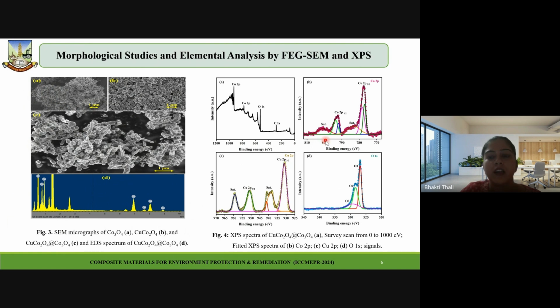Further, we have done the XPS analysis to understand the surface and the oxidation states of all the elements present in the nanocomposite. Figure 4A indicates the wide spectrum, which has copper, cobalt, and oxygen. Carbon 1s is used as internal standard, which is at 285.1 electron volt. Figure 4B is of cobalt 2p.